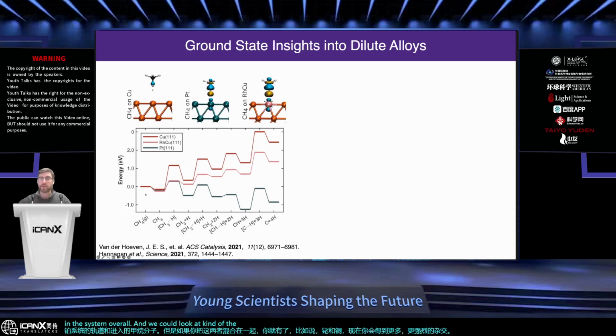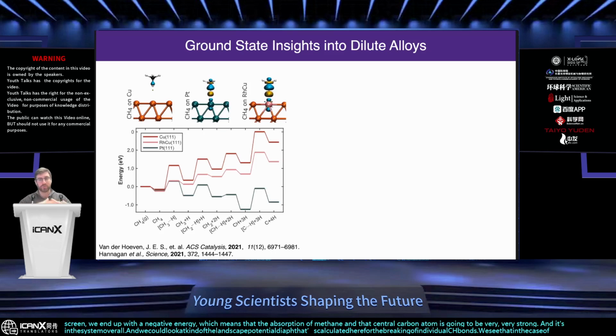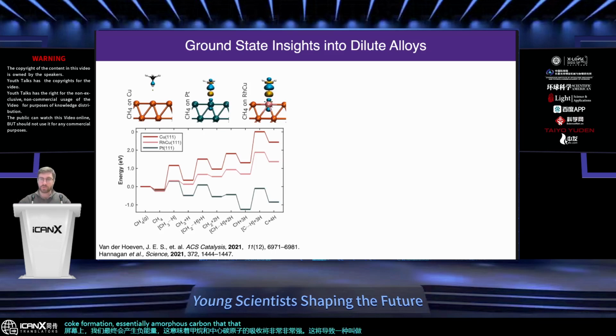And we could look at kind of the landscape potential diagram that's calculated here for the breaking of individual CH bonds. We see that in the case of platinum, if you follow the blue line on the screen, we end up with a negative energy, which means that the absorption of methane and that central carbon atom is going to be very strong, and it's going to lead to something called coke formation. It's essentially amorphous carbon that gunks up your nanoparticle surface when it's all said and done. However, if we look at copper as just an individual coinage metal, we see that there's a really high potential barrier to be able to activate the CH bond in methane. But by doping in a small amount of rhodium at the single atom level, we see that we get some Goldilocks zone. We can actually do this chemistry with very little of the precious metal of rhodium, but much reduced energy penalties, and in a regime where it's a little bit uphill, so we don't get coking, but not all the way uphill as well.